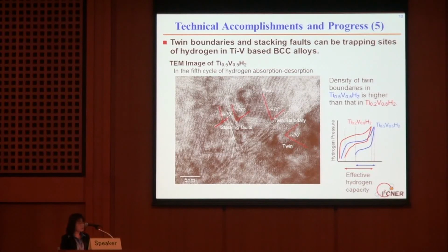Titanium vanadium hydrides have twin boundaries and stacking faults. The density of twin boundaries depends on the ratio of titanium to vanadium. The density of twin boundaries in titanium 0.5 vanadium 0.5 hydride is higher than that in titanium 0.2 vanadium 0.8 hydride. Titanium 0.2 vanadium 0.8 hydride has more effective hydrogen capacity than titanium 0.5 vanadium 0.5. From this result, twin boundaries and stacking faults can be hydrogen trapping sites.